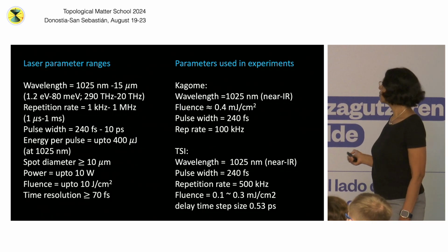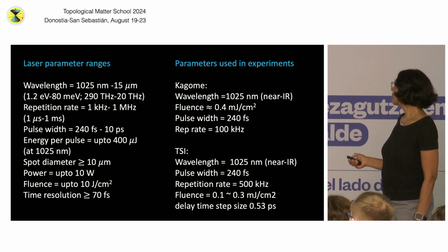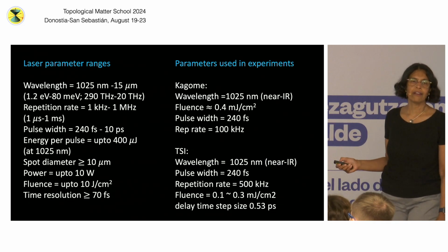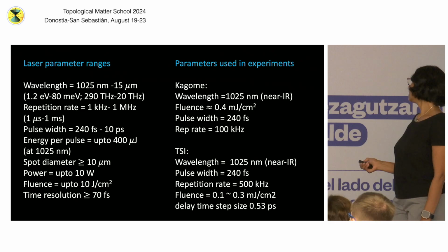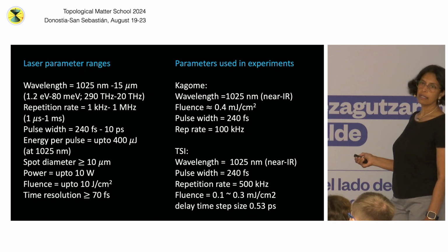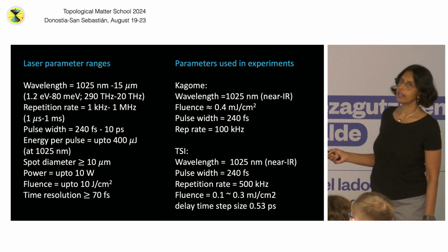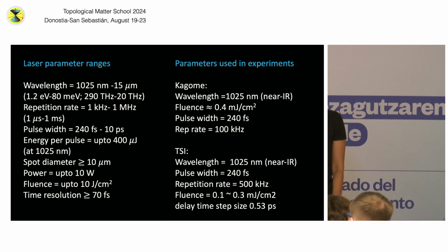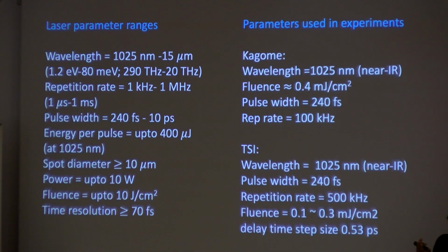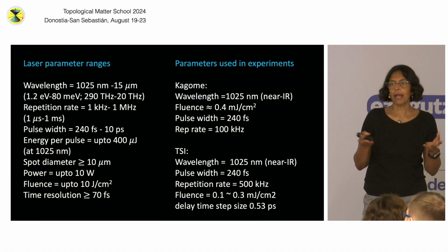The second experiment, this is where the time resolution comes in. This is a wild charge density wave system, and it's got lots of interesting physics in terms of topology. However, one of the things that was discovered recently is that the charge density wave, I'll tell you in a bit, of course, you know that a charge density wave has lowest energy excitations: the phase mode, where the charge density wave can slide. So that's called a phason. And also an amplitude mode, where the amplitude of the CDW can go up and down. That's called the amplitudon. And the phase mode is typically like an acoustic mode. It's like a plasmon, it's an acoustic mode.